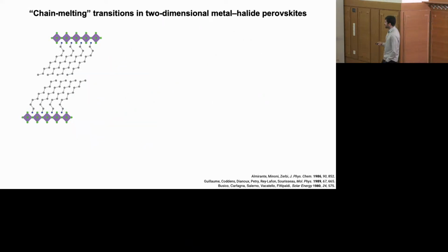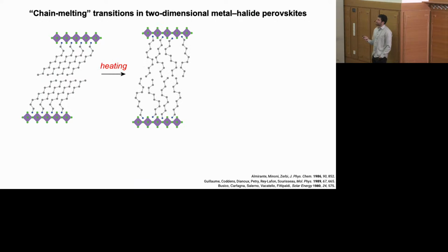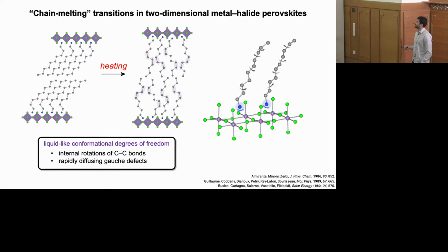But what got us excited about this class of materials was that if you heat them up, these ordered organic hydrocarbon bilayers undergo transitions to a disordered state. For hydrocarbon chains about 10 carbons long, these transitions occur very close to ambient temperature. These transitions are associated with large entropy changes that result from the fact that this is basically like a solid state melting transition. The material stays a solid, the inorganic layers aren't changing at all, but the increased disorder of these organic molecules leads to a large increase in entropy. And this results from rapidly propagating carbon-carbon gauche bonds throughout these hydrocarbon chains. In the ordered phase, you have all trans carbon-carbon bonds within your hydrocarbon molecule.